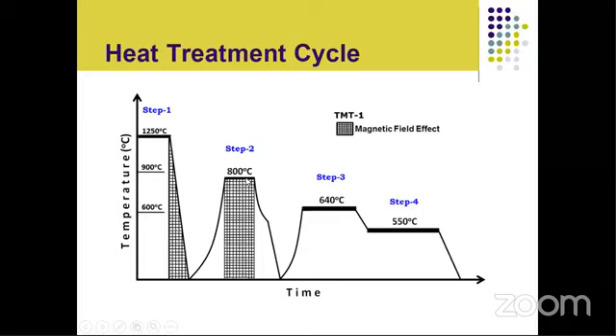But in the influence of magnetic field. That is, at the same time, when we heat this material below Curie temperature, magnetic field is applied so that the two phases, which are magnetic and non-magnetic, are under the influence of this magnetic field. So under this magnetic field, when material is heated, the magnetic phase, which is alpha 1 phase, which is iron cobalt rich phase, will respond and elongate along the magnetic field.